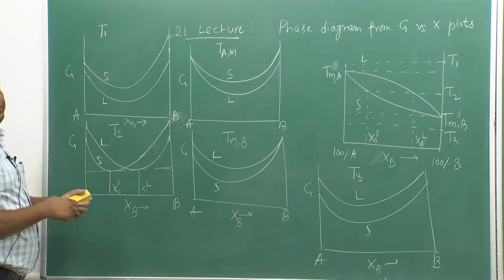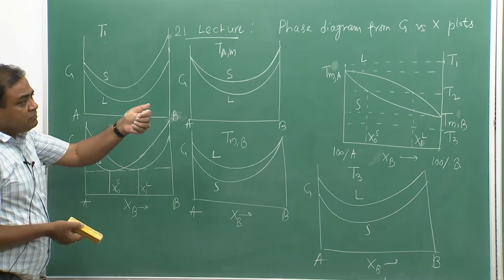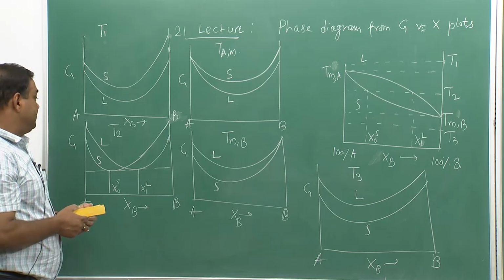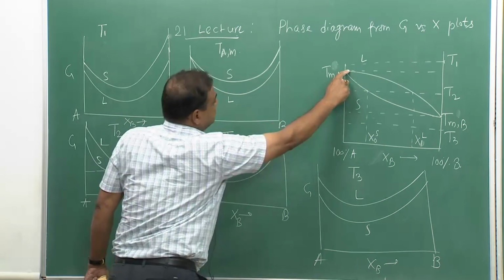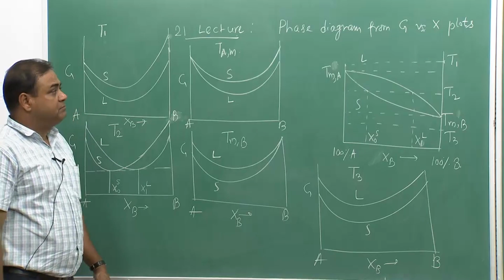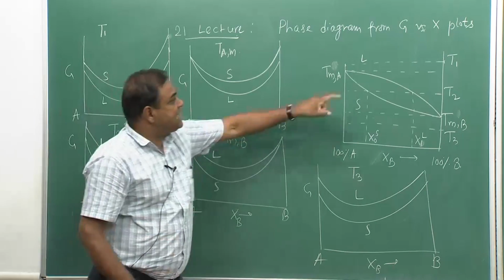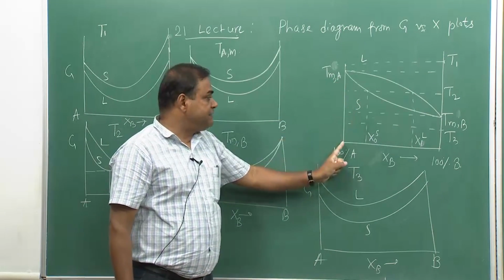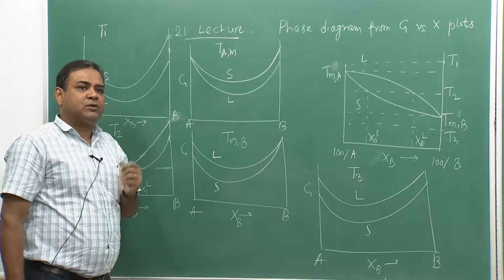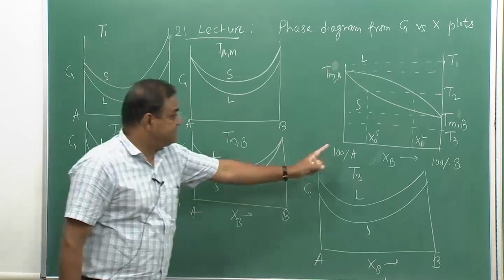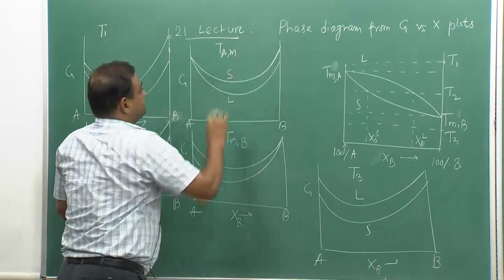As we have seen, at a different temperature we can draw the composition free energy graph if we know the mu, which is the chemical potential. Now, let us see what happens at the temperature which is the melting point of A, TMA, that means the melting point of pure A. Whenever we reach that point, it suggests that the first solid would appear in the liquid, and that would be 100% A, so we have to take this composition. Then the graph looks like this.